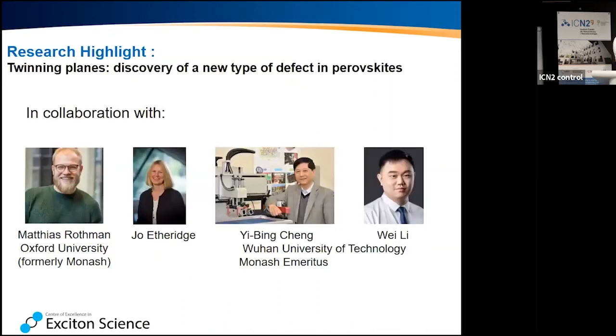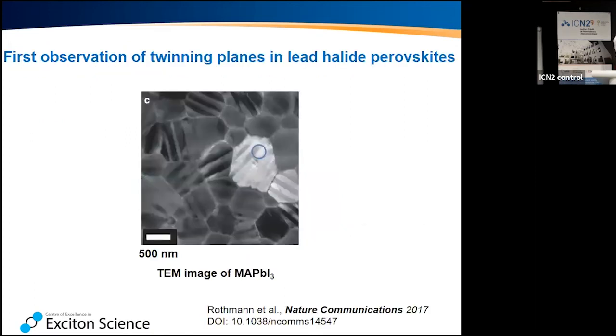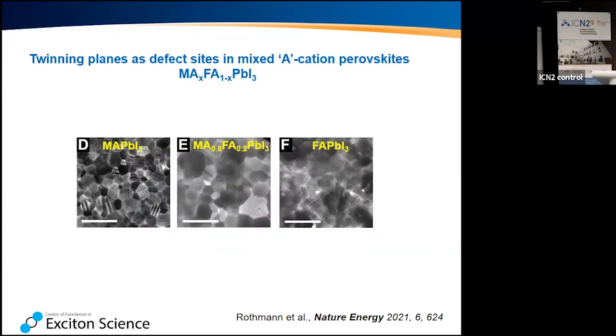And I think we also recently did some work on looking at those twinning domains in perovskite, but I think I might just jump across that. That's also done in collaboration with people at Oxford. And Matthias, have you met Matthias? Yeah, cool, just jumping on. So in a nutshell, what we saw was that if you look at methylammonium versus mixed methylammonium formamidinium and pure formamidinium perovskite, this one has a lot of these twinning domains. So it's more like a mirror axis in your crystal. And when you go to MA 0.8, FA 0.2, that's somehow the golden range. This is where we see absolutely no twinning. And then as we move on again to the pure formamidinium, the twinning comes back.